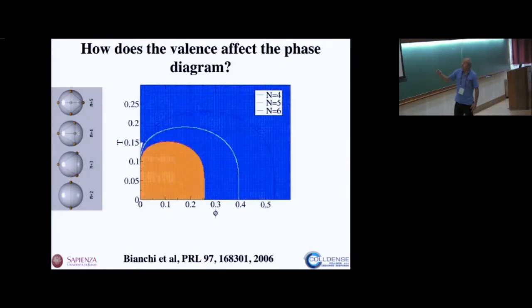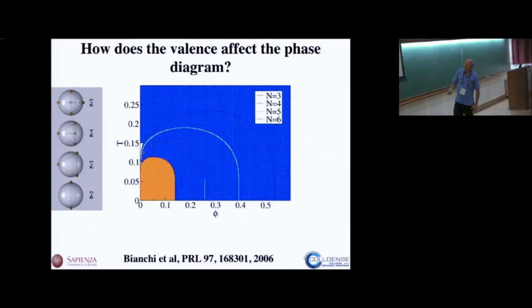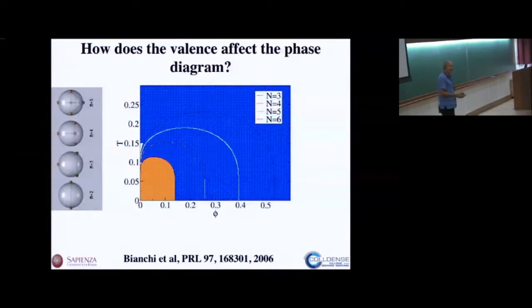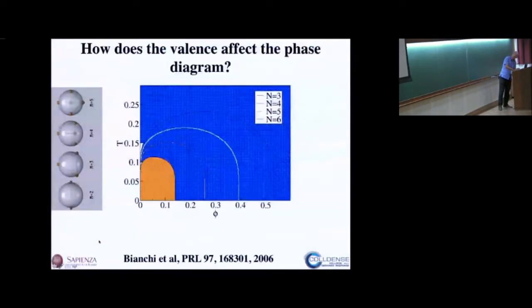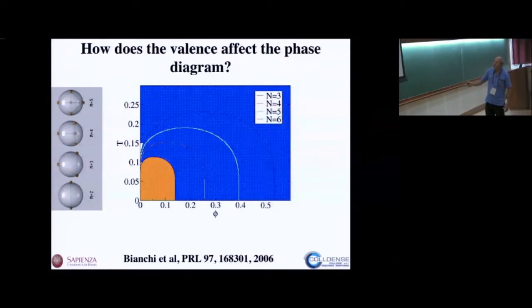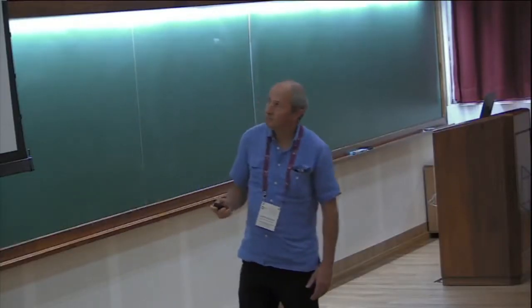You can keep doing this. We can go to a particle with valence 4, a particle with valence 3, even a particle with smaller valence than 3, if you start to play with binary mixtures of particles with different valence. Even with a mixture of particles with valence 3 and 2, you can bring this critical temperature to 0 and the critical density to 0. So in some sense, you can completely suppress the phase separation by decreasing the number of patches in your system.